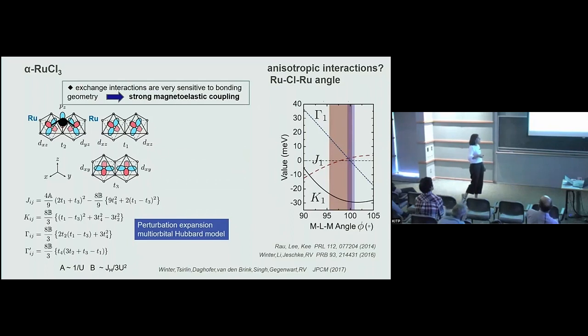And what I'm showing here is, for instance, the expressions of the exchange interactions obtained from perturbation theory in a multi-orbital Hubbard model, including spin-orbit coupling. And this is written as a function of the hybridization, so hopping parameters between, in this case, nearest neighbors. So these are the most important hopping processes between ruthenium-ruthenium through the ligand atom, in the case of ruthenium trichloride through chlorine, and then there are also the direct hopping parameters t1, t3.